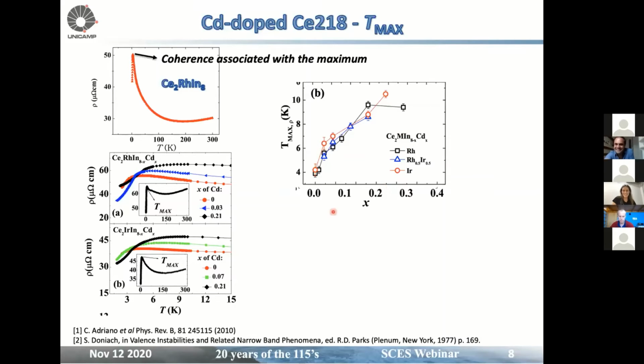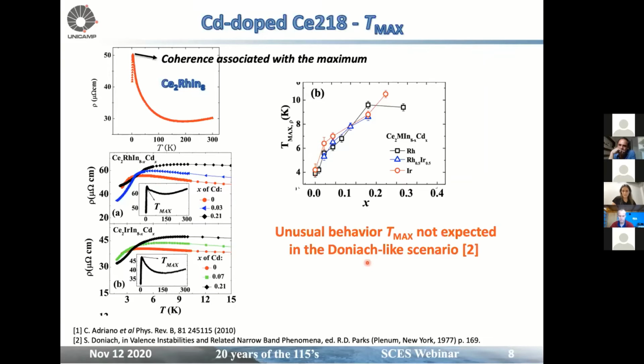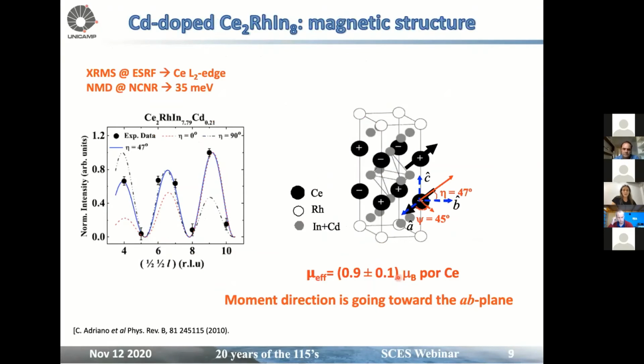And so we have Tmax as a function of x, and this is an unusual behavior of the maximum temperature from the resistivity data that is not expected in the Doniach-like scenario. So it means that from here we already know that crystal fields might be important for cadmium-doped 218. So a while ago, we determined the magnetic structure for cadmium-doped Ce2RhIn8.